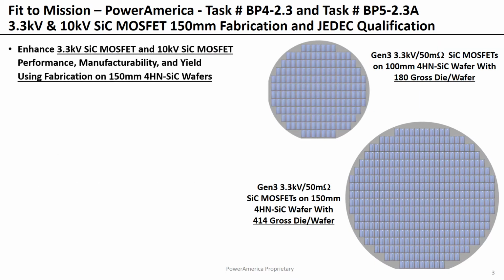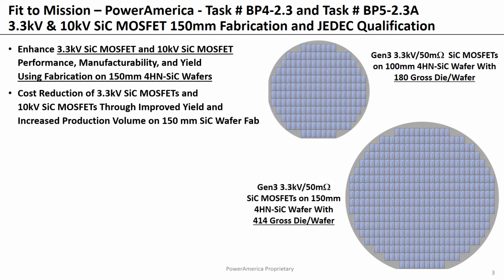In terms of fit to mission, in order to enhance the 3.3 and 10 kV silicon carbide MOSFET performance, reliability, and yield, we will be utilizing fabrication on 150 millimeter silicon carbide wafers at the Cree, Wolfspeed, Durham fabrication facilities. In addition, there's a cost reduction of 3.3 and 10 kV silicon carbide MOSFETs because of increased number of die, improved die yield, and increased production volume on the 150 millimeter silicon carbide wafer fab at the Wolfspeed Cree Durham